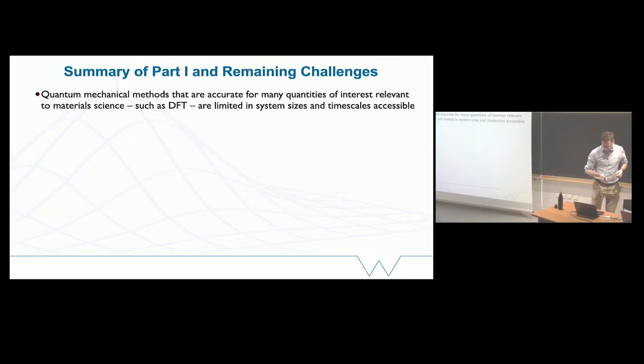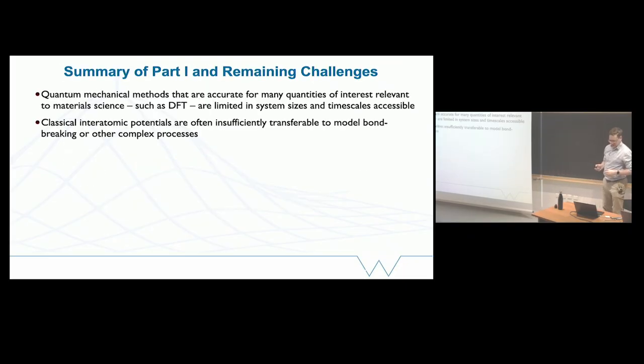Okay, if I've remembered right, this is the end of part one, so let me just summarize a bit. Quantum mechanics is very accurate in many material systems. DFT is a really good balance between cost and accuracy, but it still is limited. We can maybe do 1,000 atoms and a few picoseconds, but not much more than that. Classical potentials are really hard to make transferable. I didn't really emphasize the chemical species side of things, but I would say you can fit a good embedded atom model in a metal for maybe 2 chemical species, but not really more than that. So if you want an alloy with 5 or 6 components, it's extremely hard to do.